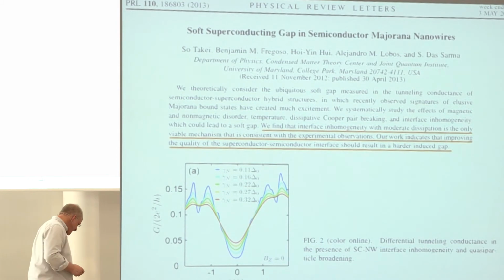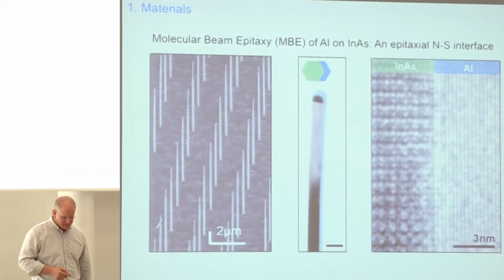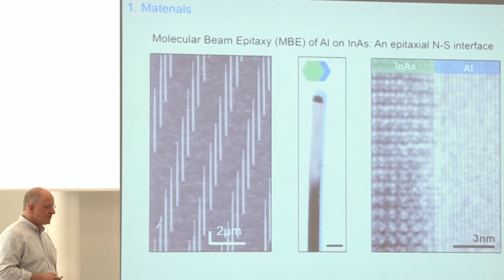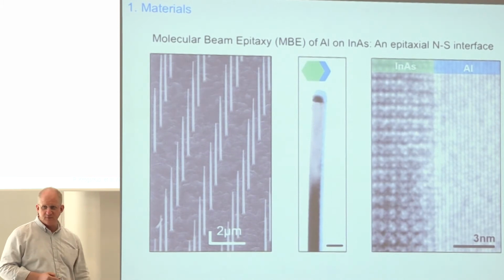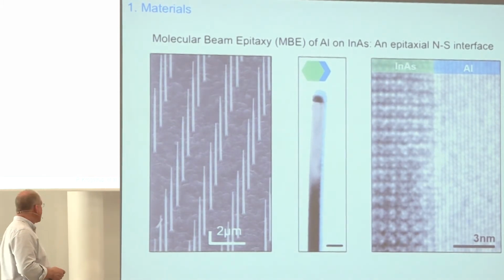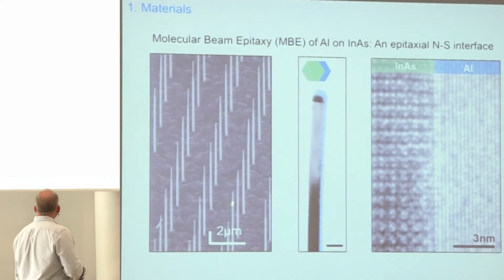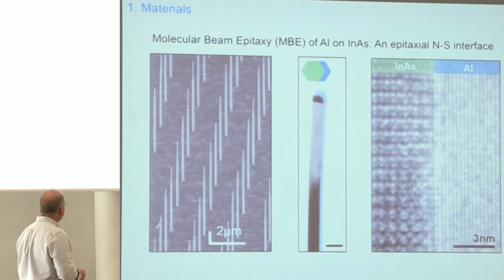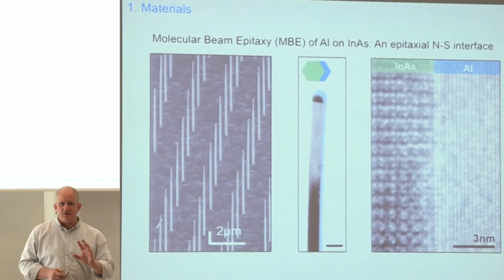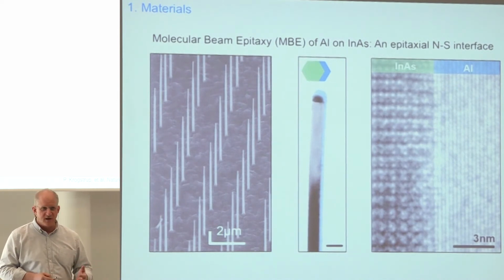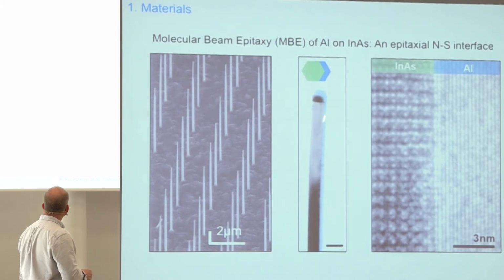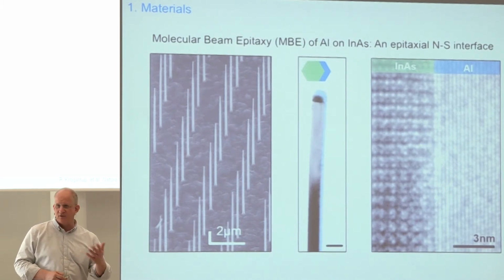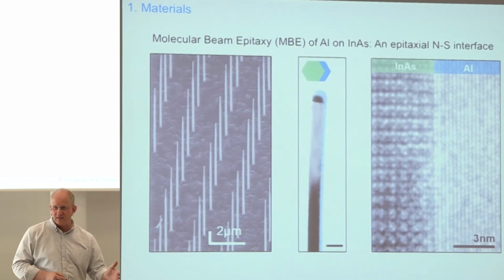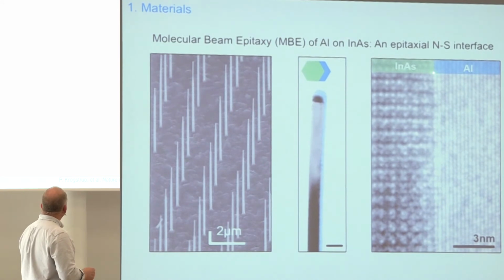And that brings me to the material science part of this talk, which has to do with the developments from the materials group in Copenhagen, led by Jesper Nygaard, and particularly pushed forward by a remarkable postdoc named Peter Krogstrup. These nanowires are grown from catalyst gold particles on an indium arsenide substrate, these are indium arsenide nanowires, and then by adjusting the temperature and the pressure in the growth chamber during the MBE growth of the nanowires, aluminum can be deposited on the side of the wires. There's already aluminum in this growth chamber because it's a so-called 3-5 growth chamber, so aluminum is already in the MBE system. You can produce an interface between the aluminum and the indium arsenide that is epitaxial.